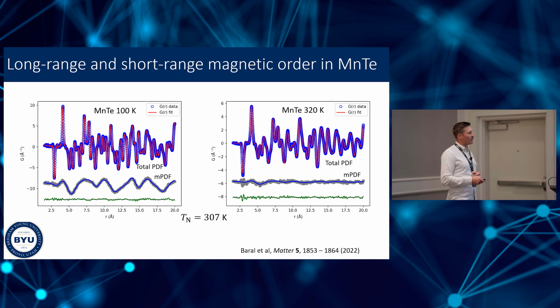So here is some representative magnetic PDF data on manganese telluride. Here at 100 Kelvin, below the magnetic ordering temperature, we have a nice, strong, long-range magnetic PDF signal because we have long-range magnetic order. Okay, we've got a great fit to it.